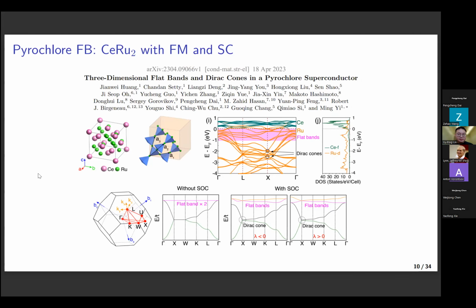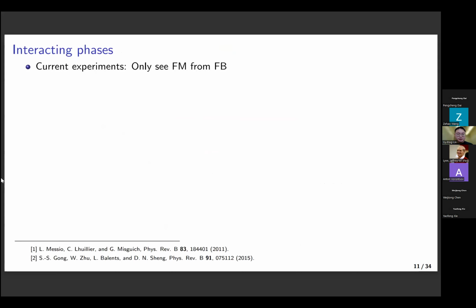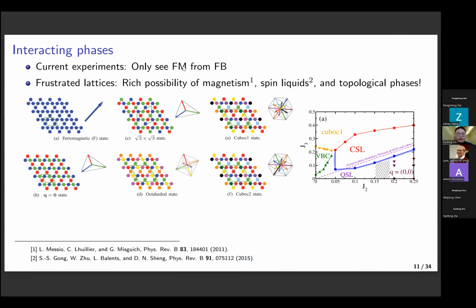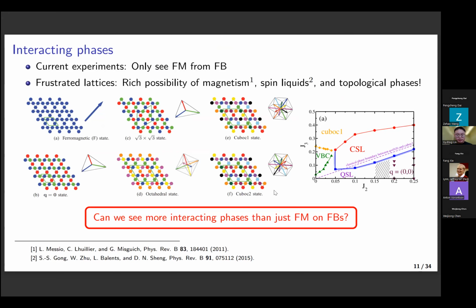So these are the experiments that we have seen in the frustrated flatband materials. Up to now, the current experiments that we have seen are only observing the ferromagnetism from the flatband. However, we know that because the materials we're considering have frustrated lattices, there have been many theoretical works proposing many possibilities of magnetism or spin liquid or topological phases. For example, for a kagome lattice, in addition to the ferromagnetism, there are also 120-degree coplanar orders and octahedral orders, or the more exotic cuboc orders. And beyond the mean field level, there is also the proposal of the chiral spin liquid and also the non-chiral spin liquid. So our question here would be, can we see more interacting phases than just the ferromagnetism if we look at the kagome flatband materials?